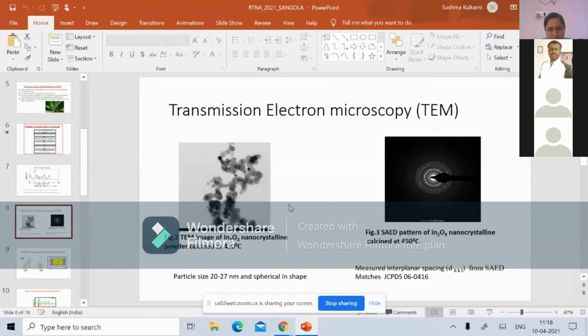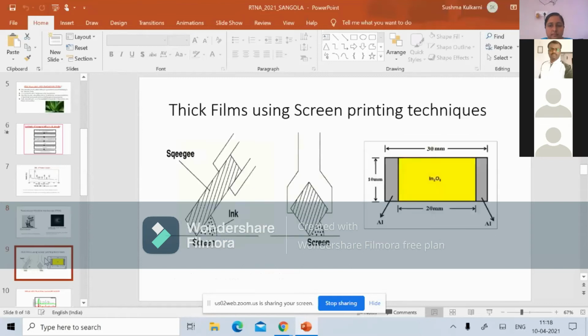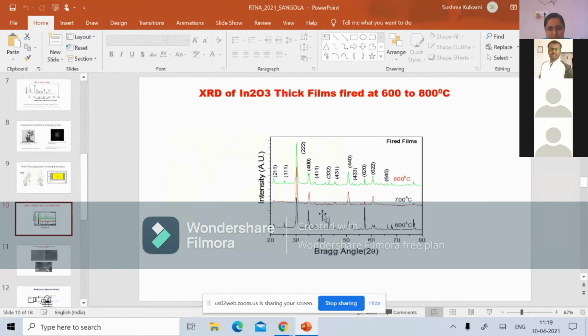Use this powder as a functional material. Using a simple screen printing technology, I have printed the thick film on the alumina substrate. This I have shown here, my thick film, and I have used aluminum as a contact for the further gas sensing purpose. And here, this is the size that you can see, the yellowish color, and this is for the contact purpose. And this is the screen printing technique that I have shown. And once the films are formed, I have fired the films at 600, 700, and 800 degrees Celsius.